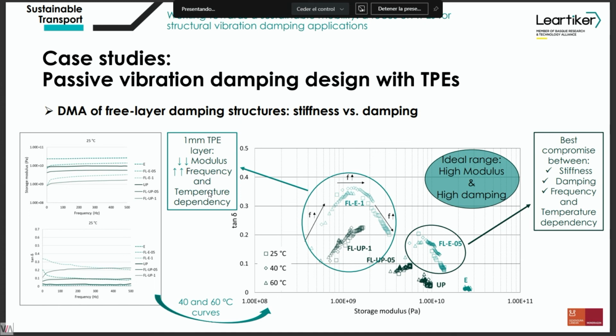If this is something that we do not want, if we want to have a material or a structure that is more stable with frequency and with temperature, then we have a best compromise between all of them when adding 0.5 to the free layer or epoxy-based SMC material. Because as we can see in the graph, in this case, we have high stiffness values, more or less similar to the unsaturated polyester SMC, and with good damping values up to 0.2. So we have moved more or less from 0.0, very low damping values, up to 0.2 by adding 0.5 millimeter TPE to the structures. And even more interesting is that in that case, we have a very low dependency with frequency and temperature. It's very stable with the frequency and temperature.